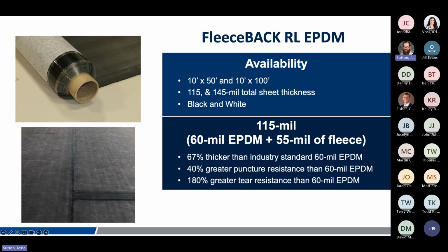But if you take a look at some of the performance increases there, and this is in direct comparison, you're looking at the bottom of that screen there, to a standard bareback 60 mil product. So obviously it's 67% thicker with the inclusion of that fleece, but it offers 40% greater puncture resistance than a standard bareback sheet and 180% greater tear resistance when you add that external reinforcement as opposed to just a bareback non-reinforced EPDM sheet.